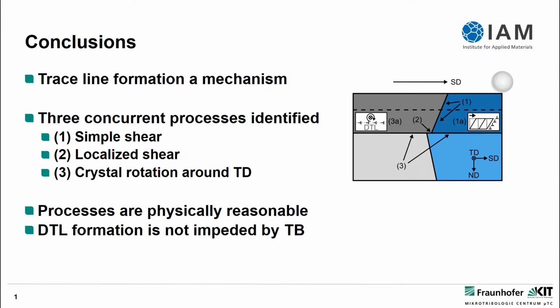With the help of this twin boundary as a marker, as a silent witness to the processes happening while the sphere is sliding that we cannot observe in situ, we have identified that there is a simple shear happening. Like in this picture, a deck of cards, we are shearing the material in the sliding direction. We have a highly localized shear at the location of the lower dislocation trace line that we identified in this TEM lamella that I've talked at length about in this presentation.